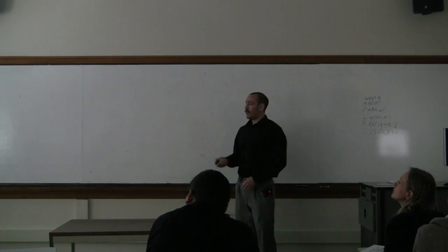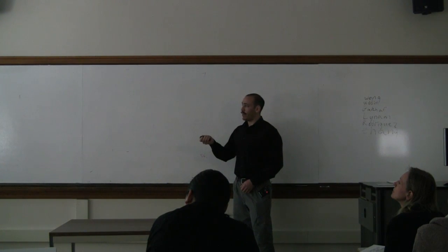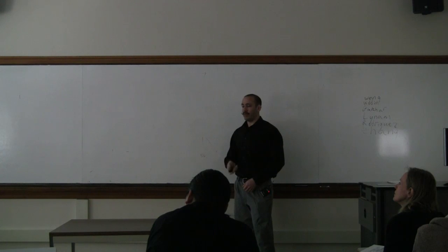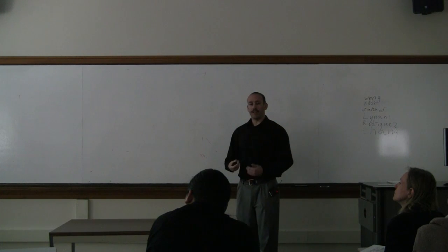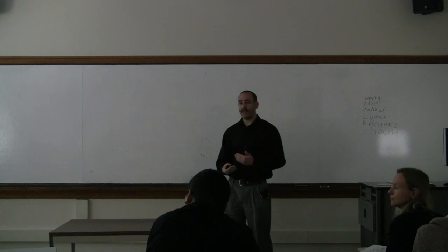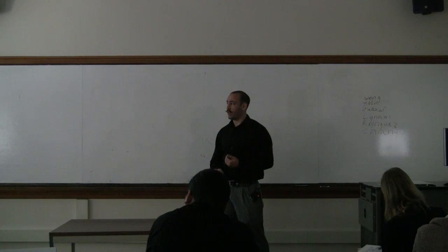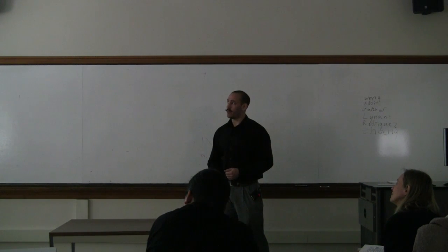Now the coating. What we have here on the left is a polished aluminum sample, and on the right we have a coated sample with the molybdate-based conversion coatings. The coating approximately took 7 minutes, and each surface was polished of the aluminum sample before it was exposed to the coating bath.